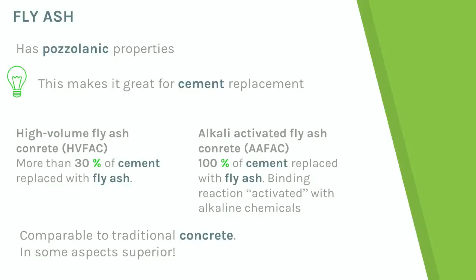There is also the possibility of completely replacing cement with fly ash, but then it has to be alkali activated with chemicals such as sodium hydroxide and water glass. These alkali activated concretes can have some properties even superior to the traditional cement concrete, but the use of chemicals makes the ready-mixed production of these concretes complicated. Perhaps they are better suited for the production of prefabricated elements. Encouragingly, more and more companies are being set up around the world, dedicated to the production of alkali-activated concrete or high-volume fly ash concrete, or concretes with other types of industrial byproducts such as slag.